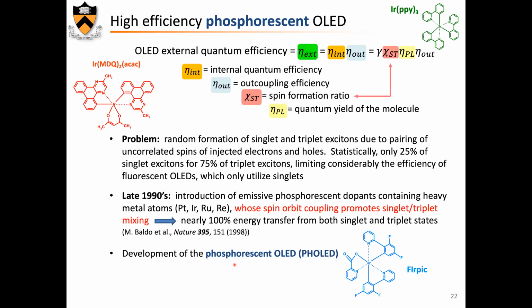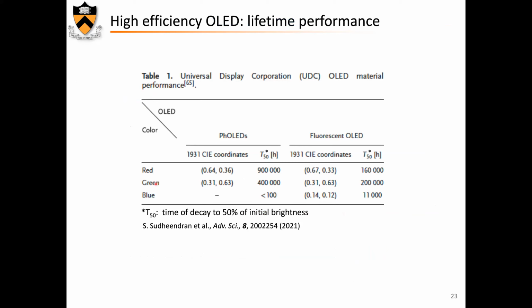And that was the development of these PHOLEDs, or phosphorescent organic light emitting diodes, that are being used everywhere today. So I just pulled some statistics on lifetime, because that's also very important for applications. If you look at fluorescent OLED, the ones without these phosphors, this is the time to 50% reduction in efficiency. For the red it is 160,000 hours, green 200,000 hours, and 11,000 hours for blue.